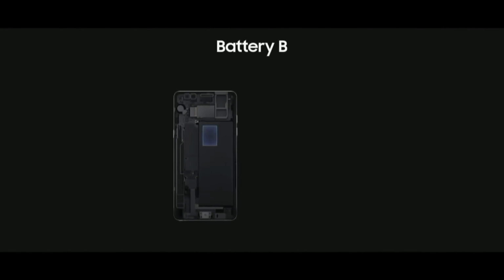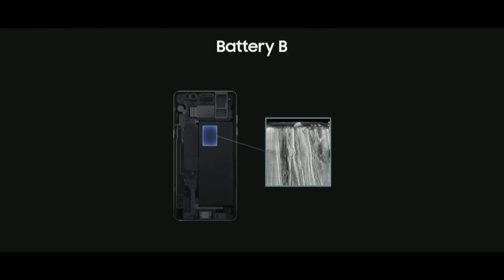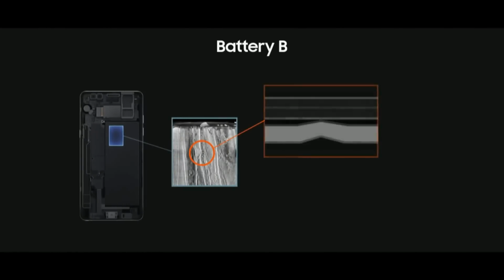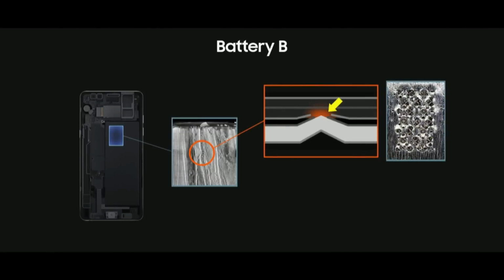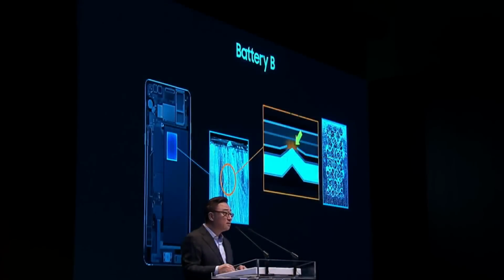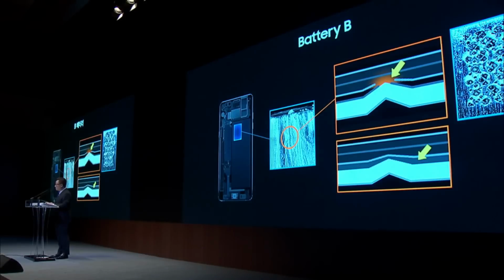When we examined battery B, we consistently found melted copper on the negative electrode area facing the positive tab, indicating a short circuit had initiated in that area of the battery. Based on our analysis, the main reason for the incident in battery B was an internal short circuit as a result of abnormally high welding burrs that formed during the ultrasonic welding process to attach the positive tab. Due to the high welding burrs, penetration of the insulation tape and the separator resulted in direct contact with the negative electrode. In addition, we found a number of batteries that were missing the insulation tape.